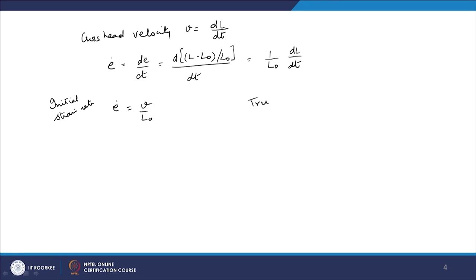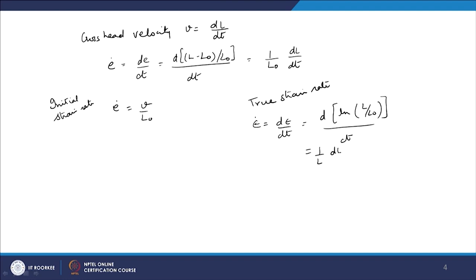And another can be my true strain rate. For that, epsilon dot will be equal to d epsilon by dt, that will be equal to d ln of L upon L naught by dt, that will be equal to 1 upon L dL by dt, that is equal to V by L. So, continuously the length is now changing. Here it was a constant length, it is an instantaneous length.